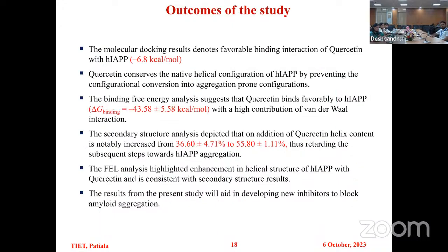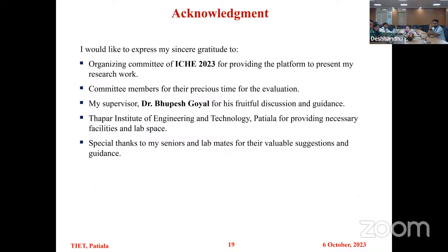So coming to the conclusion, the molecular docking results showed highly favorable binding interaction of quercetin with HIAPP, and binding free energy analysis suggests that quercetin binds favorably to HIAPP. FEL analysis highlighted enhancement in helical structure, and the result from the present study will aid in developing new inhibitors to block the amyloid aggregation.